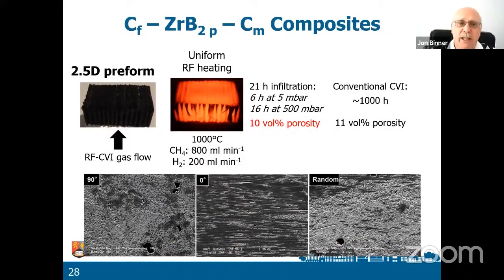Okay, so then we make the composites. This is a 2.5D preform. So this, remember, is stacked layers of fabric, and then you needle them going through, and the needle goes down, gets hold of some fibers from the layer below and pulls them back to the layer above. And so we've got something in the Z direction. We found we can get very uniform RF heating, which is excellent. And we found that after just 21 hours of infiltration, we can get 10 volume percent porosity. So it's 90% dense. With conventional CVI, to get 10 or 11% porosity, 89–90% dense, you're looking at about 1,000 hours. So in this case, it's now roughly 40 times faster.